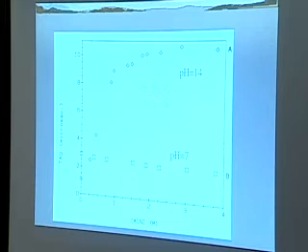But if you go to pH 14, where you have 1 molar sodium hydroxide around, you get a huge effect of the acetonitrile. It's a reversible effect. You can go backwards and forwards on this curve. That is, the acetonitrile does compete for surface sites and stop the oxidation of water. So there's some fairly direct evidence that there's an inner sphere charge transfer mechanism happening when you try to oxidize hydroxide at an electrode surface. So this not only happens at a molecular level, but it happens at an electrochemical level.